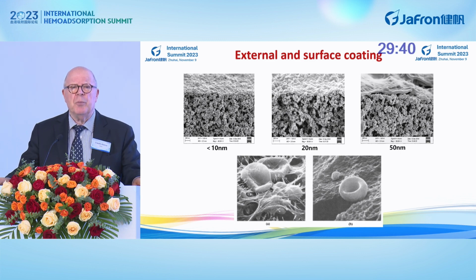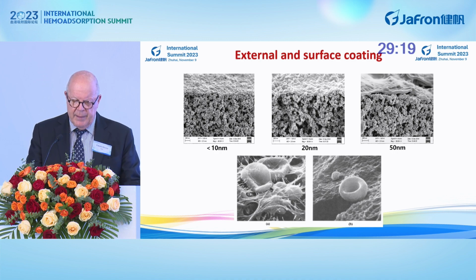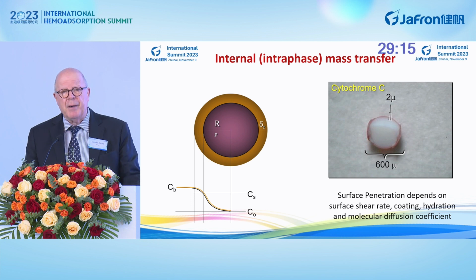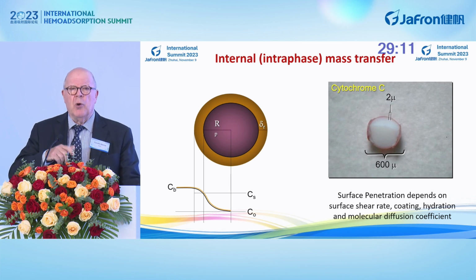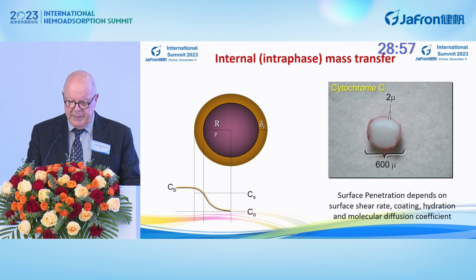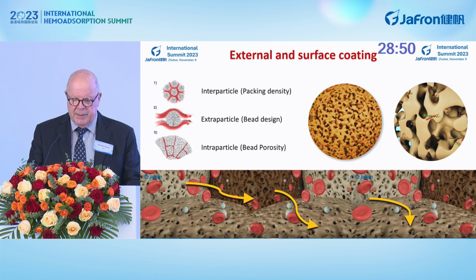Of course, in order to prevent interaction with cells and major proteins, the external surface of the sorbent needs to be coated. And there are coatings of different thickness, and there is a development today of a technology to make coating very, very thin in order to prevent interaction with cells. However, there is a problem because when you try to coat a bead, the diffusion of the solute inside the bead may be limited. And this was one of the first experiments we did almost 25 years ago now on an original sorbent that showed that the coating could not really permit diffusion of the solute inside.